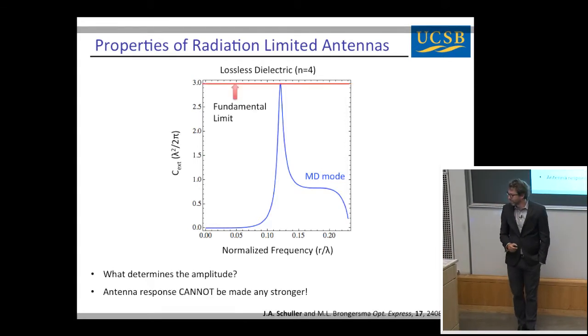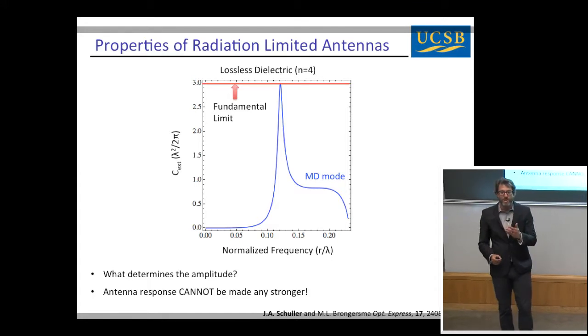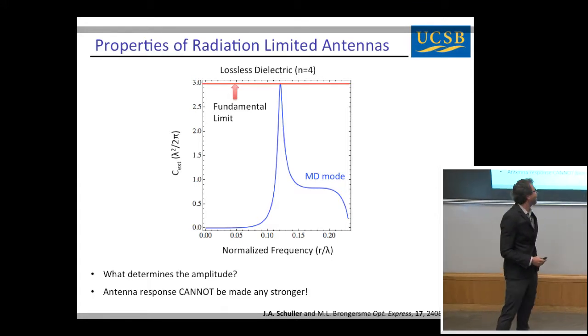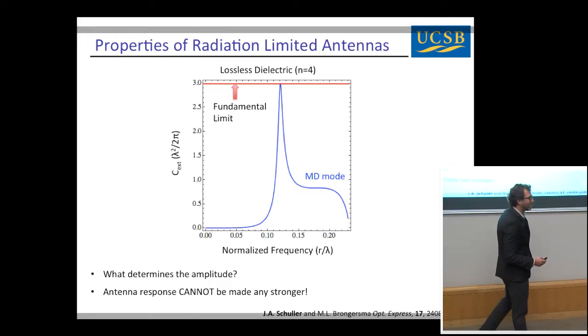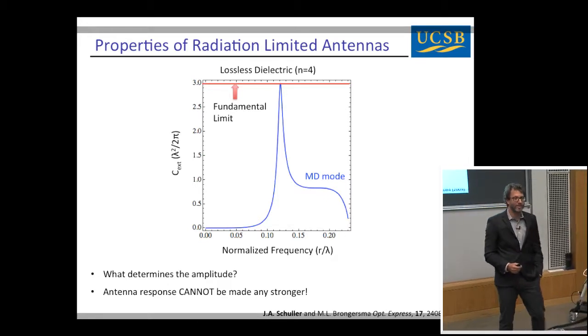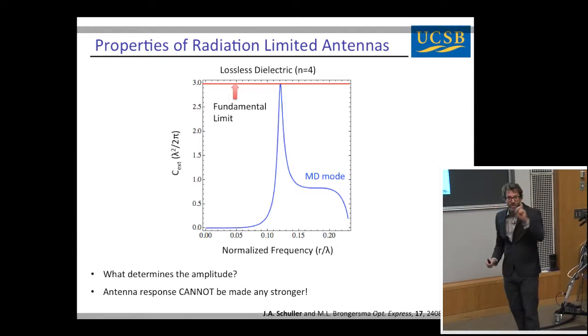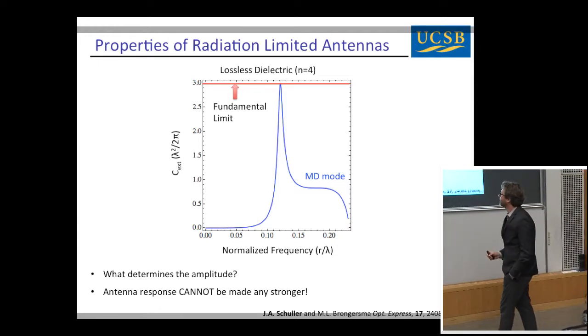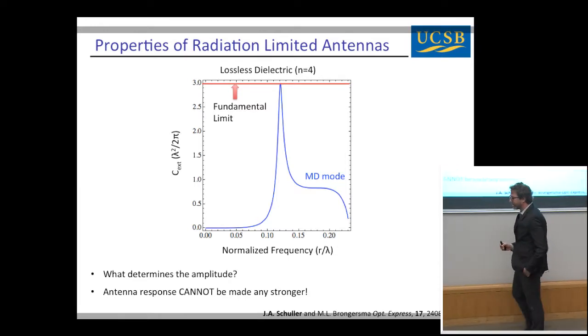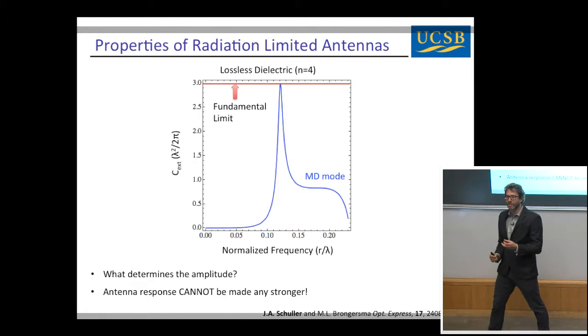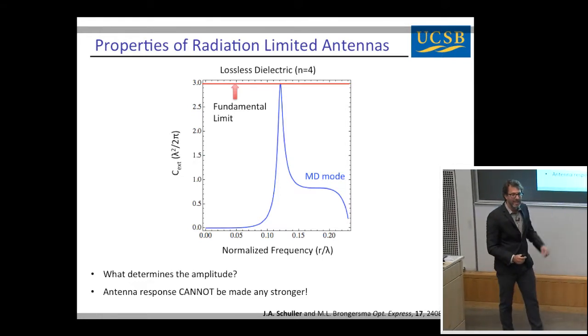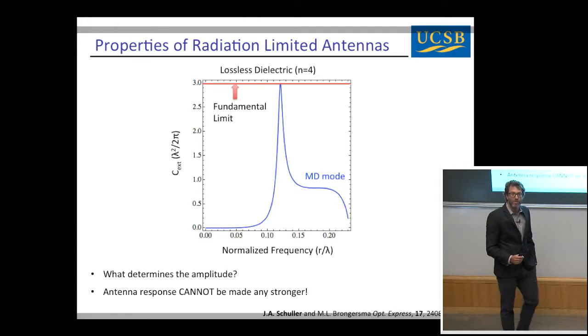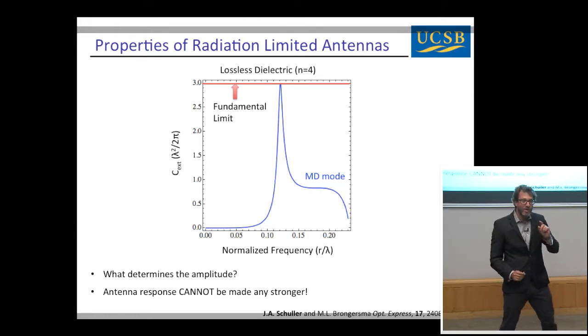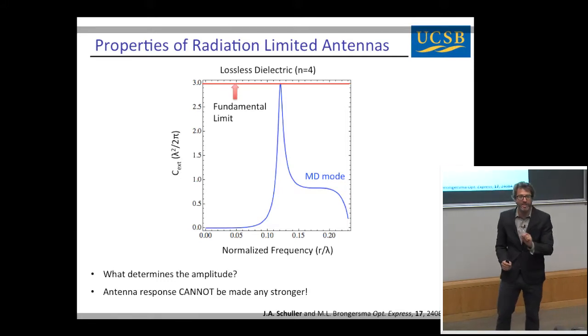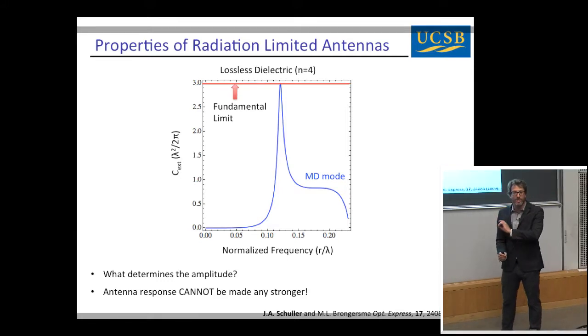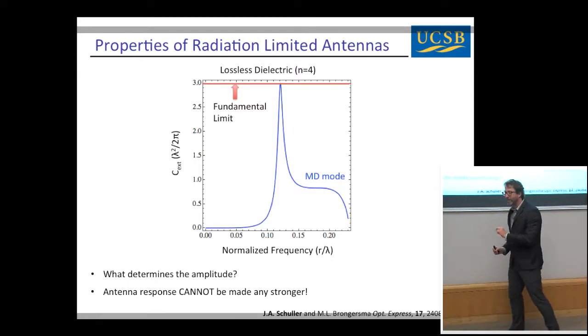Well, it turns out, as I've shown in the past, that there is a fundamental limit to this dipolar scattering cross-section. It cannot possibly be larger than 3 lambda squared over 2 pi. Again, it's important to understand this is just for a single mode. We can also show that a semiconductor or dielectric resonator with no losses necessarily has to reach this fundamental limit, which is to say that our antenna cannot be any better. It is as good as you're going to get. There's nothing you can do to this material, or by changing its size and shape, that will give it a better multipole response.